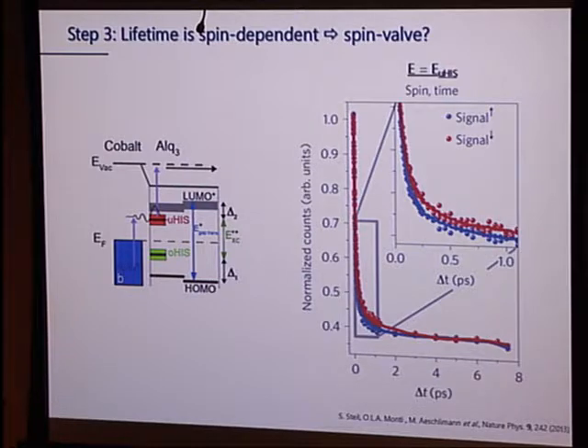Again, this is our energy level scheme here. We excite that hybrid interface state in that first layer, and now we're going to ask, what is the lifetime of that excited state? How does it evolve in time? For this we do time-resolved pump-probe two-photon photoemission spectroscopy, and you get curves that look something like this. You see that there's a small difference here. When you zoom in, it's actually a larger difference. You use a three-level optical Bloch equation system to try and resolve that dynamic.